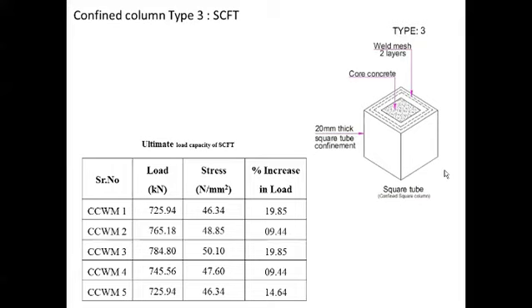Now, over the circular shape, what happens with the square shape? We tried to handle these two shapes separately. When we used the square shape, the stress values were ranging from around 46 to 50 Newton per mm square, and load carrying capacity was increased only up to 20%. So circular shape is advantageous over the square shape, that was the reference we have drawn here.